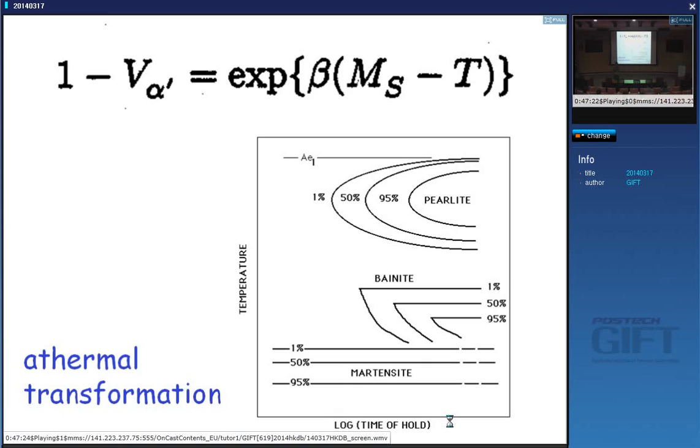So it's a very good question: this athermal characteristic, is it always the case, or if martensite forms at a high temperature, can you also get isothermal transformation? So this equation here doesn't have any time in it because the time scales involved are so fast that in an experiment we don't observe the fact that the transformation is evolving with time up to a certain limit. Okay. So, if it's growing at 5,000 meters per second, then your experiment doesn't detect the evolution of the martensite. So if you alter your alloy chemistry such that you slow the transformation down, then you can get isothermal martensite.